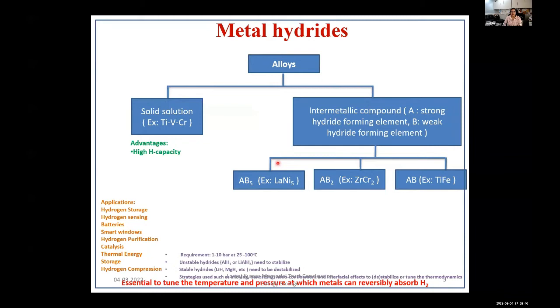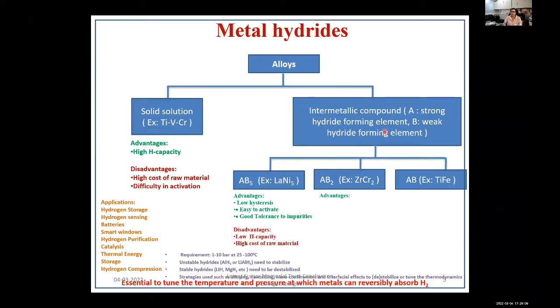So if we start with the metal hydrides, then there are different classes of metal hydrides. These are either intermetallics, wherein you have a combination of a metal element A and another B, where these can be alloyed together to form either AB, AB2, A2B, AB5, or A3B7, and several other alloys. And each of these has a separate characteristic. Just to give a few examples, the AB5, the well-known example is lanthanum nickel 5.